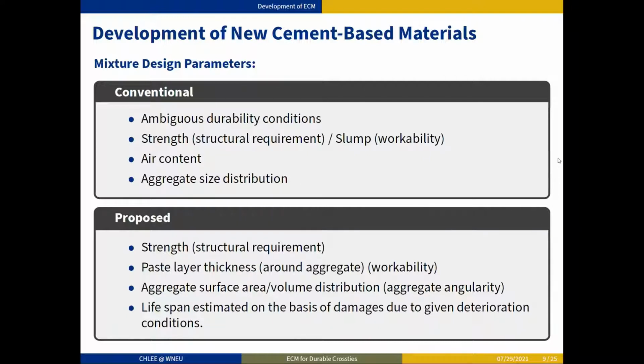However, when we developed the new ECM, we thought about new design parameters. Strength, as conventional, is one of the parameters that we have to consider. And instead of the slump, we thought about paste layer thickness.